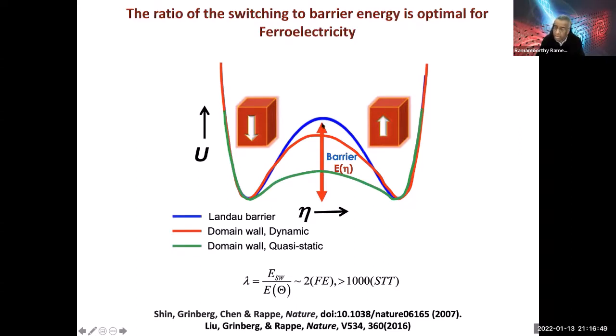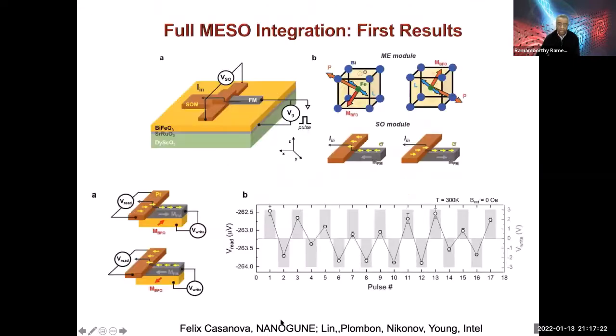That barrier could be very different. While in reality, in many real applications, it's something that looks like the red curve, where it's still domain wall nucleation and growth limited, but it's in a very dynamic mode where it can be limited by the growth of the domain wall or by the nucleation of the domain wall. So understanding these differences is still very key. And we haven't done, as a community, enough measurements. There are some really beautiful theory papers. I'm citing two of them, Andy Rappe's papers, but I think we need to set up more measurements to do these dynamics really carefully. Okay, now I want to finish up in the next 5 minutes or so.